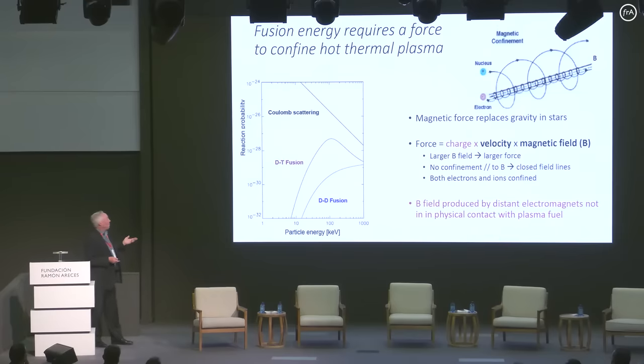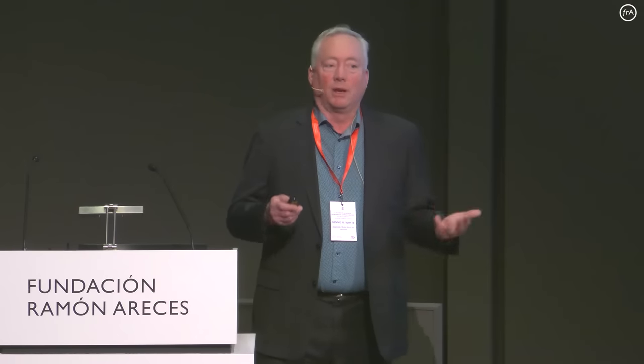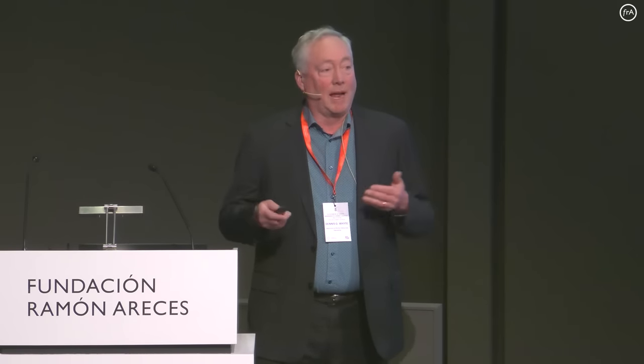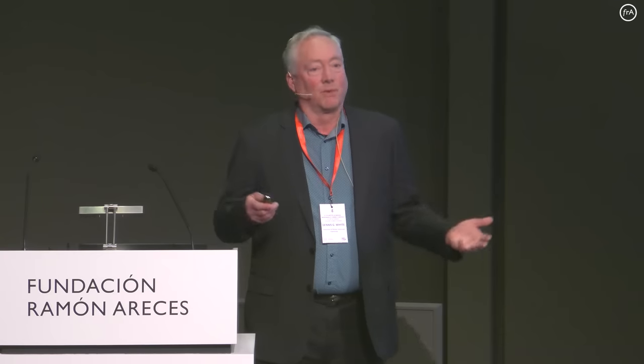So why is this required? People often confuse this, because they say, when are you going to get fusion? Well, we've made fusion in laboratories for 80 years. That's not the challenge. The challenge is that when you put it into this state, the particles scatter off each other much more frequently than they produce fusion reactions, and therefore you must allow all the particles to be hot. This means it must have a temperature, and that means it must have a containment system. So we use the magnetic force to replace gravity in the stars.